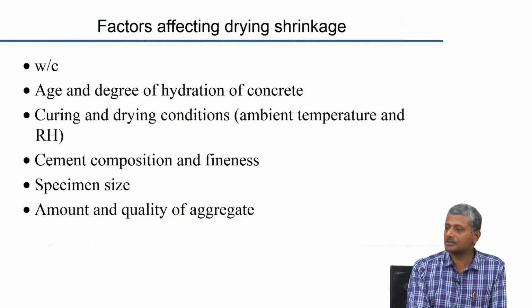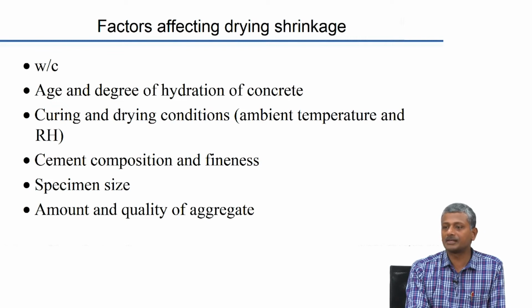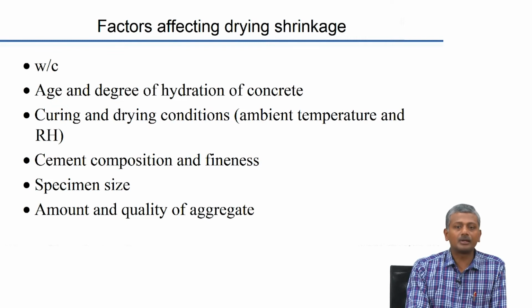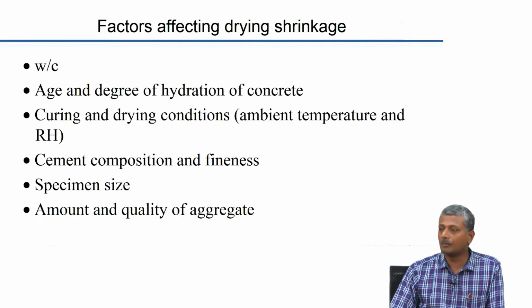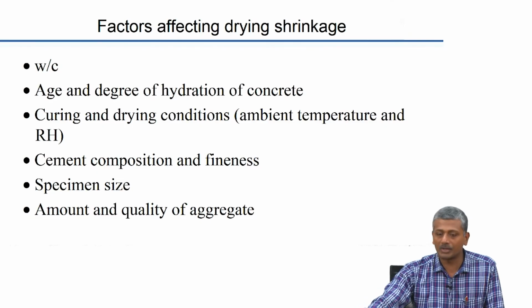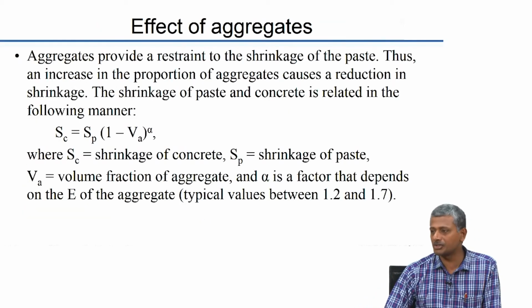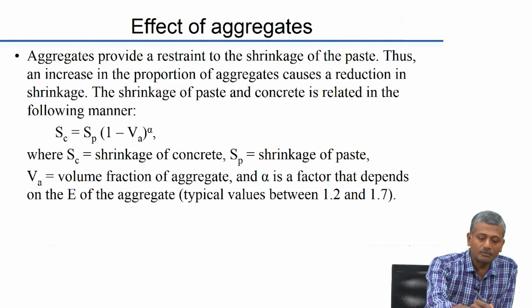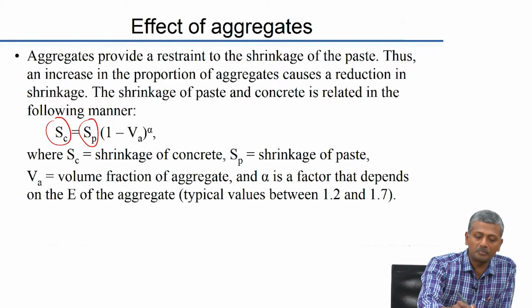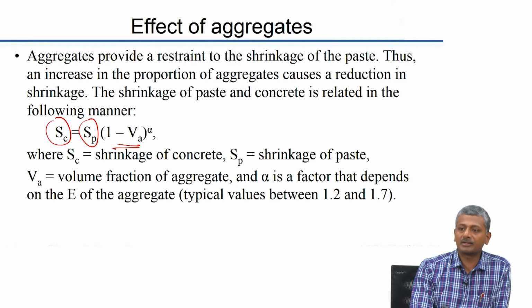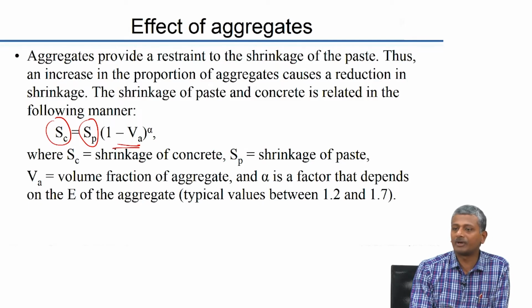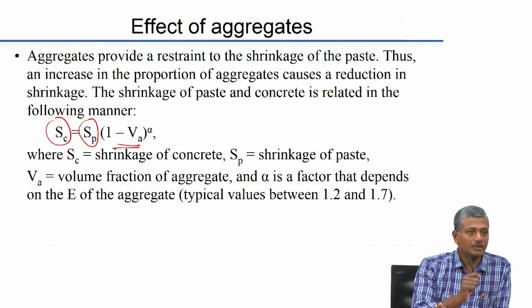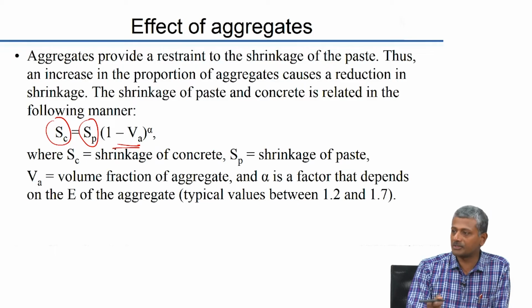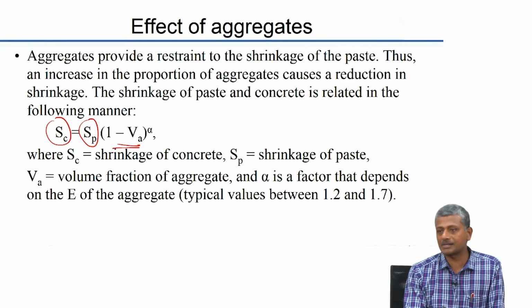The specimen size, the larger the specimen size, lesser will be the shrinkage, but then the larger the specimen size, more possibilities of differential rates of shrinkage on the outside and the interior. And the amount and quality of aggregate again is very important. Of course, this is the same sort of relationship that we saw in creep. Shrinkage of concrete is given in terms of shrinkage of paste and a factor which is inversely proportional to the amount of aggregate in the system. Okay. So, shrinkage of concrete depends on shrinkage of paste obviously, but then the aggregate acts like a restraint.